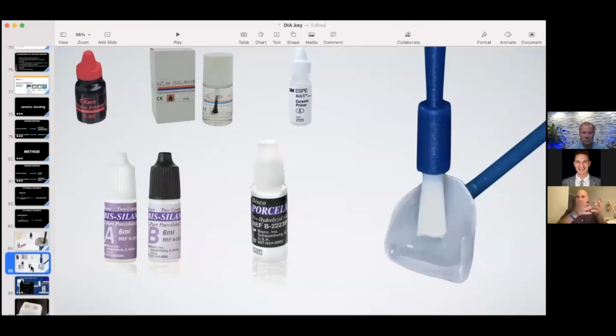They both have an expiration, but the 1-part silane is usually 18 months. The 2-part silane goes up to 2 years. But think about this. How many of you have bought a bottle of silane and it expires in your office and you're not done with it? It's because you're not doing that many restorations, which is fine. So having a 2-part silane, that's where it becomes interesting. If you're doing a veneer, you need silane. If you're doing a crown and you decide to use a concoction like Monobond Plus or Ceramic Primer Plus, that's fine, because you have retention from your prep. A veneer doesn't have any retention. This is where you need to optimize your bond, okay?